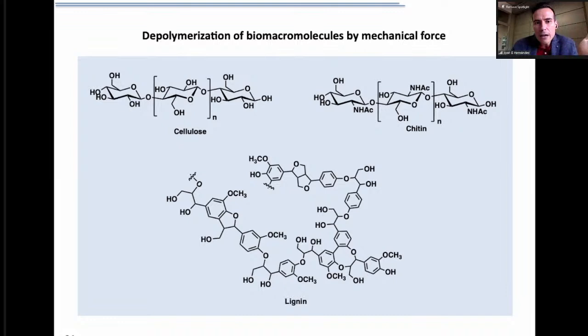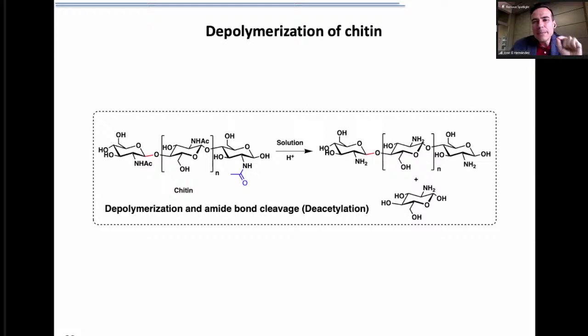But sometimes when those studies were carried out, they observed not only that the reaction could proceed mechanochemically, but the reaction was much better than the reaction in solution. In some cases, different selectivity was observed. And this is one of the cases. Previous reports on the depolymerization of chitin had demonstrated that in solution, what happened is that, for example, you would have two reactions operating.